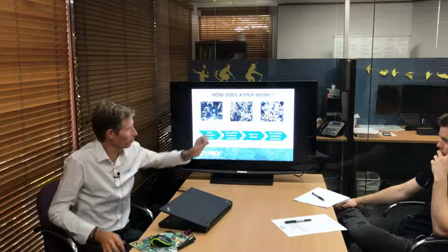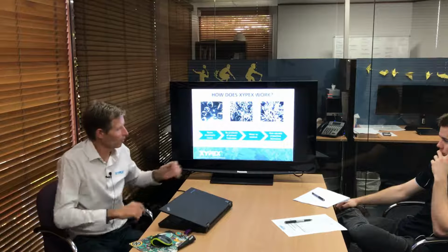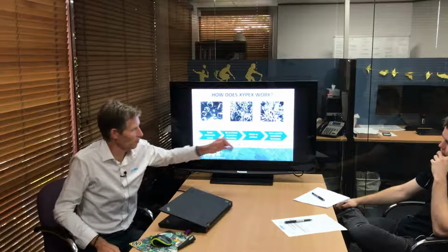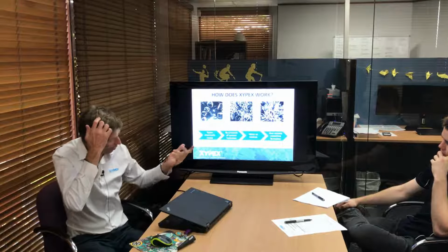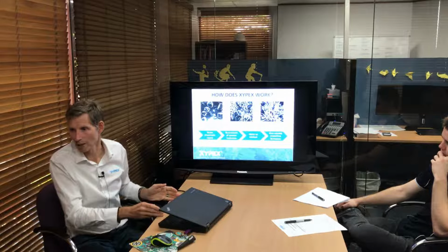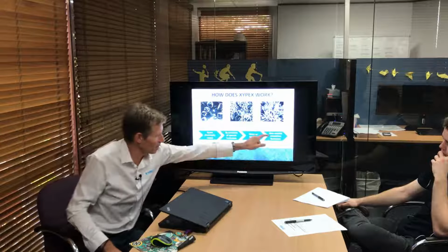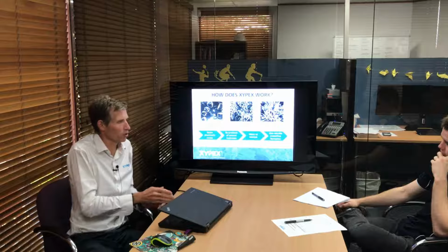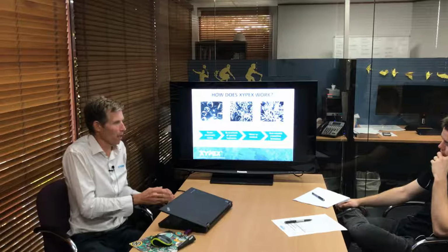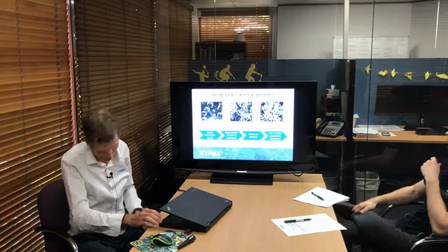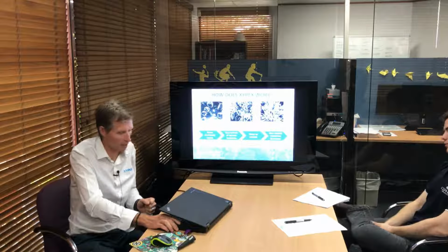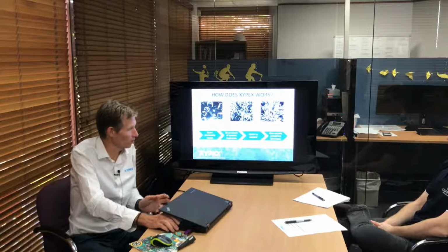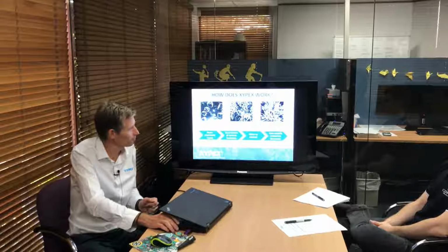As you can see from these rhombic particles, you start to get insoluble crystal growth. Now that takes place really within your 1 to 7 day period. And then what you start to get is a real dense interconnected pore and capillaries with the crystalline maturity within 21 to 28 days within the concrete structure. The key thing is, as it says, they're non-soluble crystalline formations. And I'm not sure if you picked up in the animation, it remains locked in the concrete and is permanent for the life of the structure. So it's a permanent treatment for concrete, which can give some real value add to projects. It's not something that needs a reapplication process or a retreatment; it is purely there and done at the time, permanently locked in.